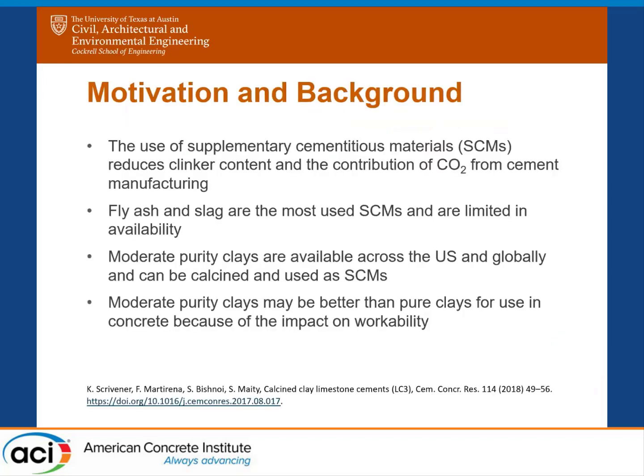A little bit of background for the session. The use of supplementary cementitious materials, or SCMs, reduces clinker content and the contribution of CO2 from cement manufacturing. Fly ash and slag are currently the most used SCMs, but they're limited in their availability and quality. The moderate purity clays are available across the US and globally and can be calcined and used as SCMs. So these moderate purity clays may even be better than pure clays like metakaolin for use in concrete because of